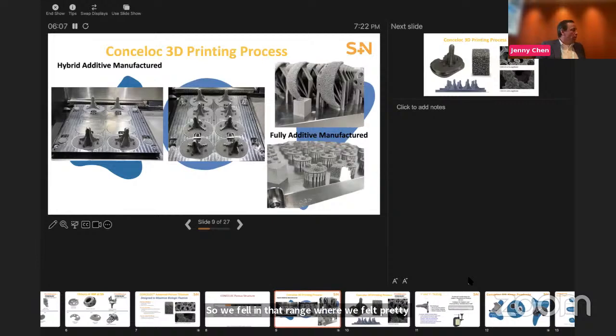So from a manufacturing standpoint, as I said earlier, we looked at fully 3D printing the base plate, and there were random porosity into the solids as you basically flip the base plate over and machine your lock detail for accepting of the polyethylene. And we found porosity, and random fatigue testing showed that this was not going to be successful for us. So what we did is what we called a hybrid, where we took a raw titanium and put this in our basically our DMLS machine, and basically printed on top of that base plate. And as you see there, the keel, the pegs, and all of that is fully 3D printed, as well as the Conceloc structure. On the hip side, it's fully added to manufacturing our patella and our cups.